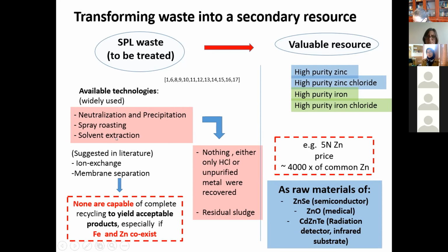Then there is also solvent extraction. It is quite good because we can get the hydrochloric acid and also the metals as salts. The zinc chloride or iron chloride can be used as fertilizer. But the investment for this equipment is quite high. Then in some literature, we also have ion exchange and membrane separation, but these processes still have to be combined with other processes, and the result has not met an acceptable product yield, especially if zinc and iron coexist in the liquid.